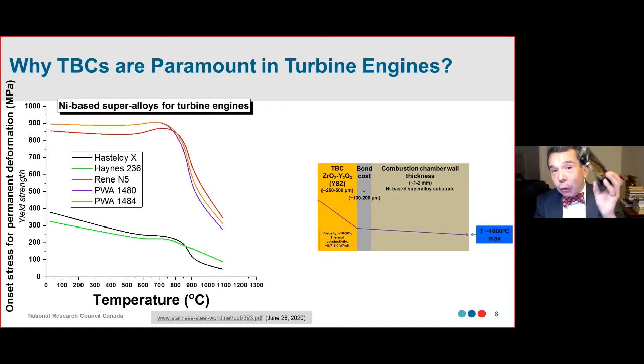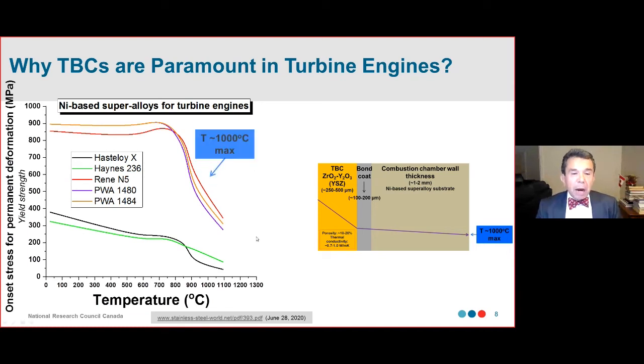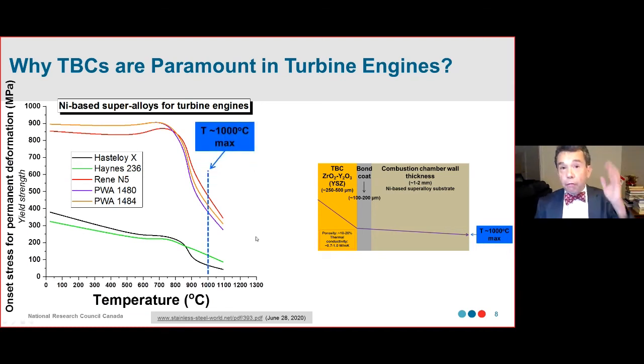So you do not want to have a combustion chamber that's going to be in this way, right? Above the elastic point. And therefore, as you can see in this graph, by about 1,000 degrees Celsius you are very, very close to the limit of a kind of catastrophic failure. To make a long story short, this is the time when structural engineers are crapping their pants. So when we're close to 1,000 degrees Celsius, the structural engineers say, don't go over 1,000 degrees Celsius. In a simplified way, that's why the limit of this material is about 1,000 degrees Celsius today.